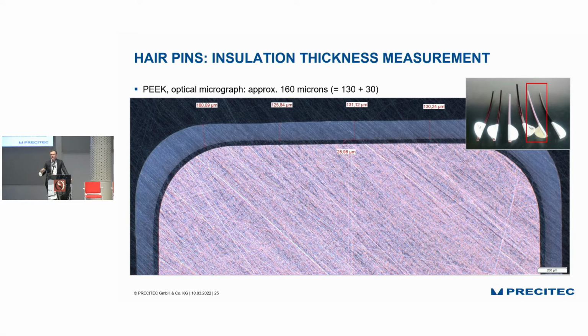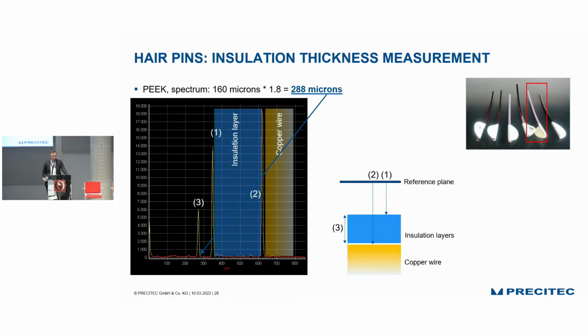And the question is, can we measure this with our optical sensors? And the result comes next. Indeed, we can. We have this 160 microns as a geometrical thickness. We multiply this by the refractive index of the material, which is the factor 1.8, and then end up at the optical thickness of 288. And this is what can be seen here. This is the first peak between 250 and 300, and the other peaks here correspond if we make a measurement via OCT going over a mirror.